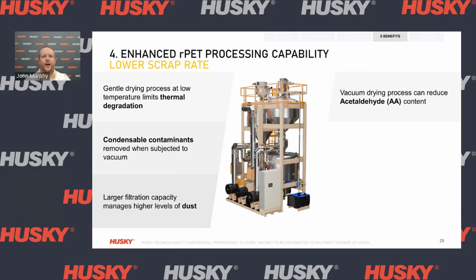Due to the gentle drying process, the vacuum dryer is excellent at avoiding acetaldehyde generation. This is mostly due to the limiting of thermal degradation, and some rPETs can come with higher levels of AA. It is also worth noting that the closed loop integration with the Husky injection molding machine can help to reduce AA levels by recognizing key processing variables like screw torque and injection pressure.